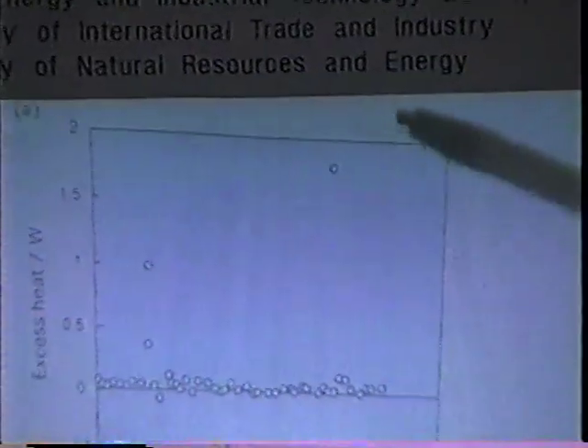Okay, this is a heat burst. We observed a maximum heat burst of around 1.8 watt. And at the same time, we detected an increase of the electrolyte temperature. Please come over to our seat and discuss with us. Thank you.